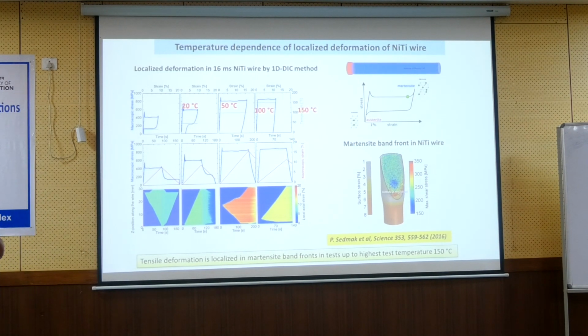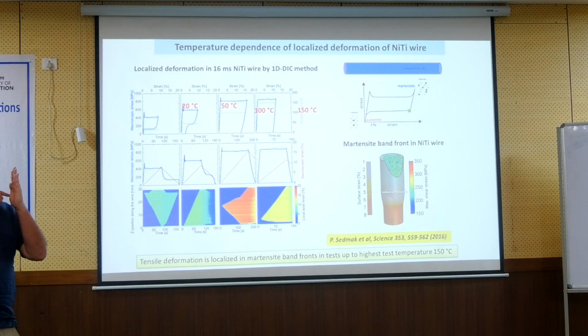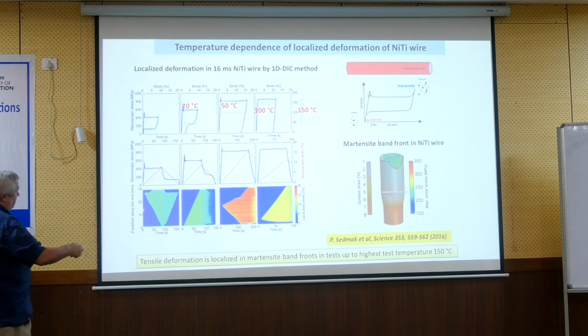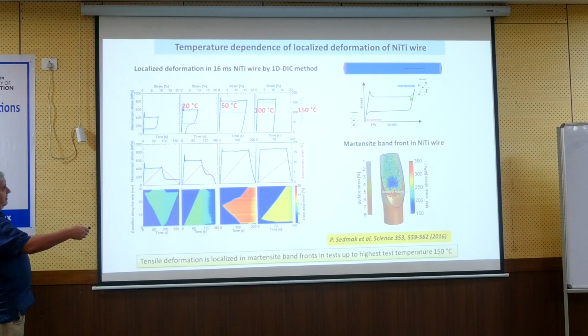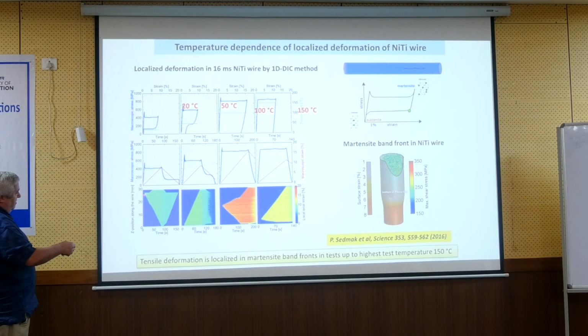Digital image correlation is normally used to visualize 2D strain on the sample. But because we have a long thin wire, we have 1D digital image correlation. This is the length of the wire, 30 millimeters long, and this is the time. If you see the line like this, it's this band which propagates from this direction to here. The color is the strain. The strain changes from blue to red, like a 7% strain, and it occurs at this time, in this position. Do you understand it?